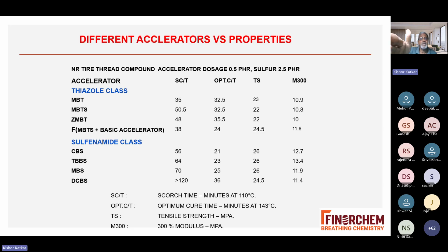Optimum cure time is not much affected. Obviously, F is again a mixture of accelerators, acidic and basic with MBTS, and that is why the cure time is different. But in case of CBS and TBBS, you can see 21, 23. Modulus is also almost the same. Obviously, DCBS gives the higher optimum time because we have seen in the graph, it is not giving the cure rate that CBS and TBBS give.